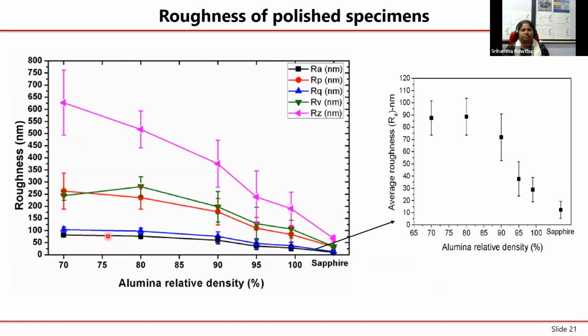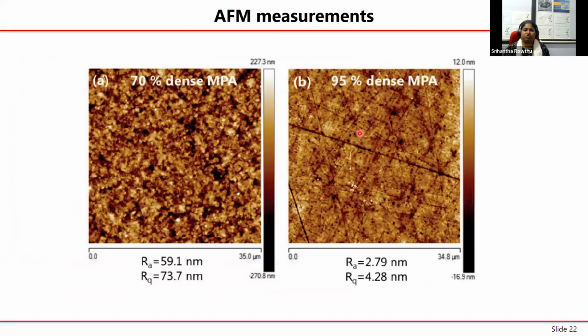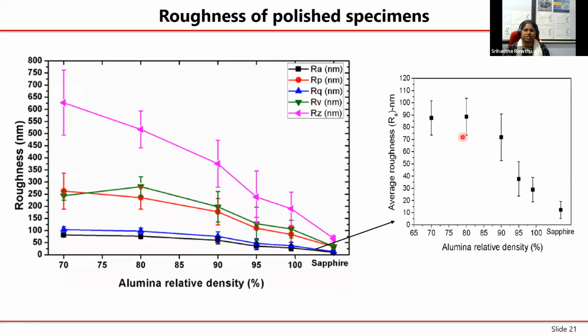And if you simply zoom in on this Ra value, this is the trend. Although it seems flatter, because very high values are given on the y-axis, the average roughness Ra value is again decreasing with increase in density. We have also confirmed that with AFM measurements and saw a similar trend. Exact values we don't get, because in the AFM we used tapping mode, while in this case we used contact.